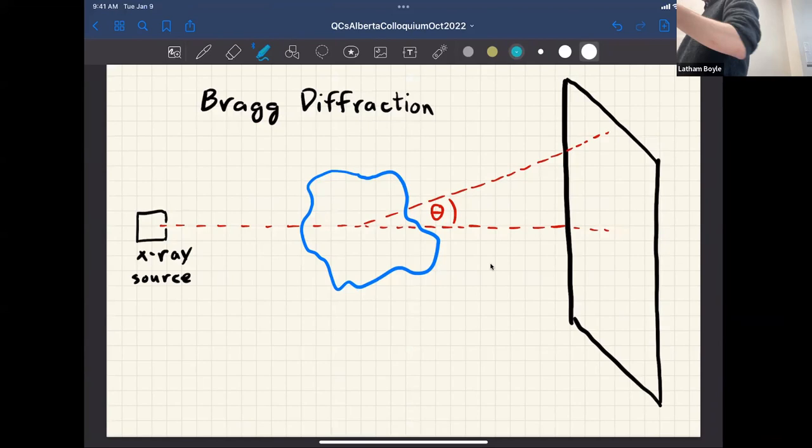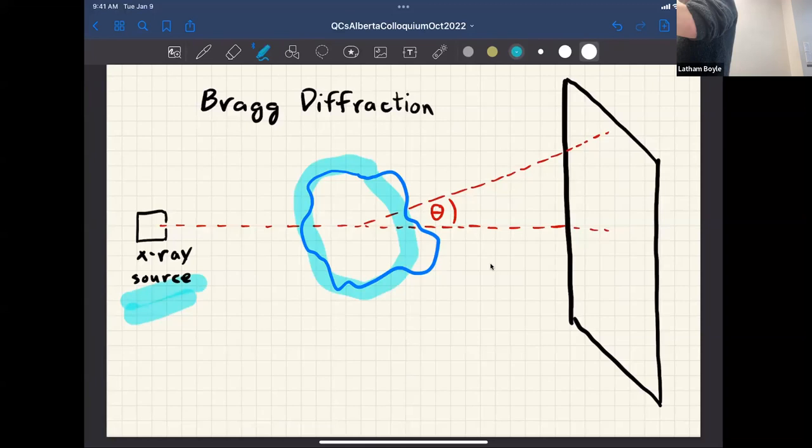Well, if I give you a hunk of matter, one classic way that a physicist will try to determine how the atoms are arranged in the matter is by doing some sort of diffraction experiment where they shine something through the matter and then look for the diffraction pattern coming out the other end. So, for example, we could take an X-ray source here, shine X-rays through our hunk of matter, and then as the X-rays come out, instead of just passing straight through, some of them will be deflected off at certain angles, and we'll get some pattern of bright and dark spots on a screen on the other side of